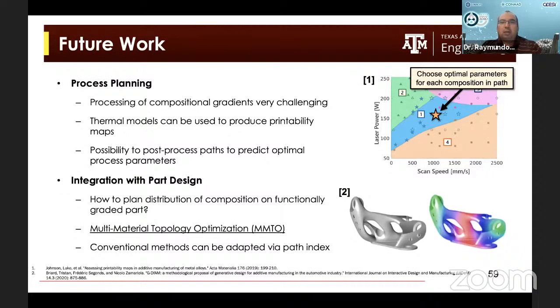Okay, so the future work that we have for functionally graded materials is process planning. It turns out that processing of compositional gradients is extremely challenging, because if you change the chemistry, you change the thermophysical properties, and if you change the thermophysical properties, you change the physics of printing. So in principle, every time that we change composition, we potentially have to change the processing conditions to make sure that we always have optimal processing conditions for every chemistry that we're trying to print.